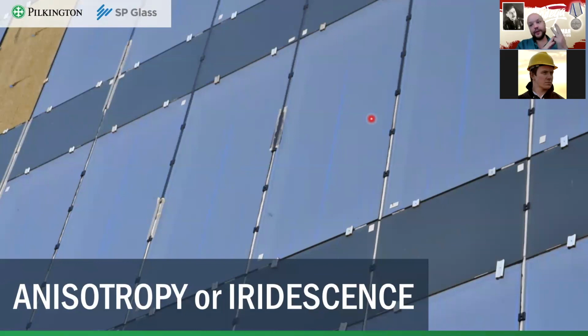First one is the light conditions. If you have a lot of polarized light, like your building stays near the sea, high up in the mountain, where the polarization of light is different, or you might have snow there. If there are a lot of reflections everywhere around, this increases the chance that you will see this picture.